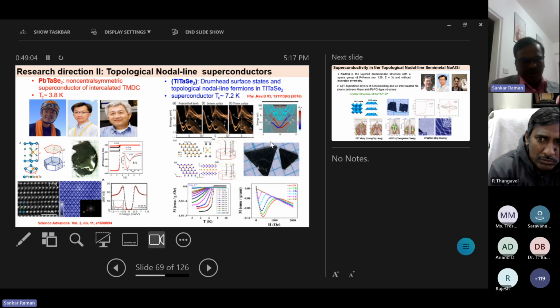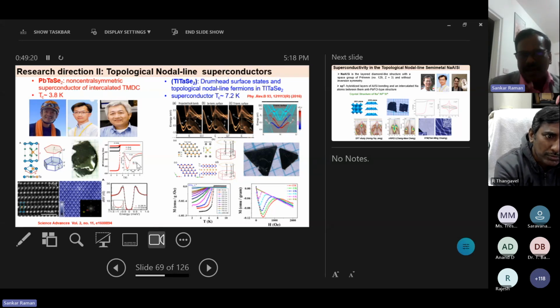I already told you why single crystals are very important. You can clearly see on the right side the MH data, the magnetic measurement data. The parallel and perpendicular measurements show a superconducting fraction almost three orders of magnitude higher than the normal one. You can clearly see the red and black. The black is the parallel one, the red is the perpendicular one. See how much difference there is in the superconducting fraction.